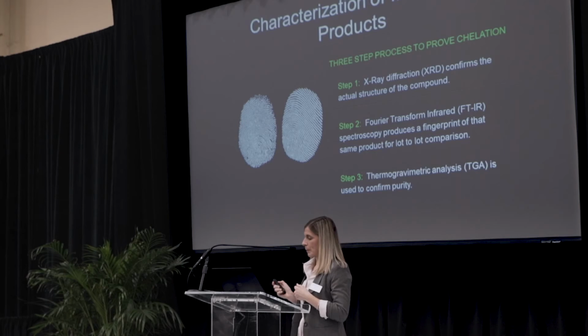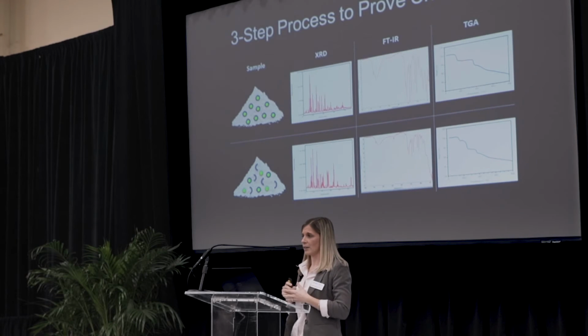Using the combination of X-ray diffraction, FTIR spectroscopy, and thermogravimetric analysis, we can use all 3 of these different fingerprints for comparison. So just to show you across the board what that looks like, if we have sample A, which is our fully bound, our reacted product, and again sample B on the bottom, which is our 50% reacted, we can compare the data for all three of these.